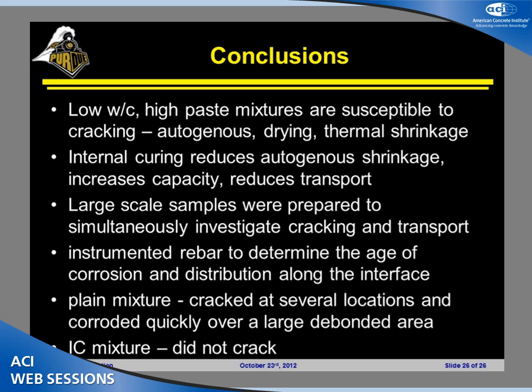So you can have two crack widths with different covers. The crack widths are the same, but you have completely different behavior. One of the reasons I believe is likely this debonding. And this debonding, I think, is really important because, the first 2 or 3 times we saw the data, it's a substantial distance that the chlorides are able to migrate along the bar.